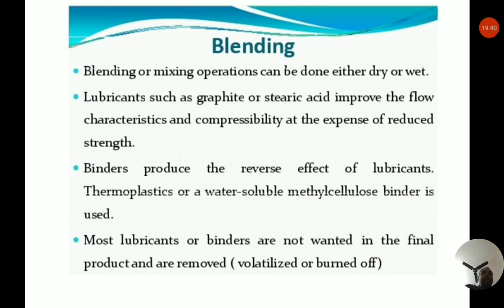Okay. Now, the powders are also mixed with additives to help the alloying process as well as lubrication. And the main function of the lubricant is to reduce the friction between the powder and the die walls, core rods, etc., where the powder slides during the compaction process. This ensures the desired uniformity of density from top to bottom of the compact. The lubricant also helps in reducing the friction for easy ejection of the compact and minimizes the tendency to form